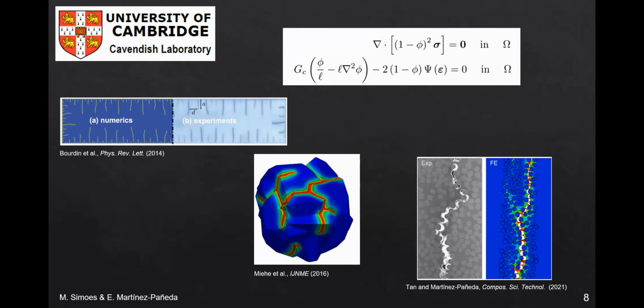So at the end of the day, we have a model that is physically sound, based on Griffith and the thermodynamics of fracture, and at the same time, computationally very compelling. You can get a good overview by looking at the balance equations. The first equation is the solution to the deformation problem, the standard balance of linear momentum with the phase field degrading the stiffness of the solid. And the second equation is the phase field evolution, sort of a competition between the strain energy density of the solid that increases with mechanical straining and the toughness, a material property.